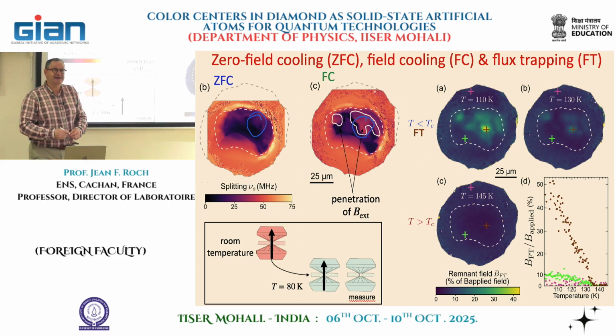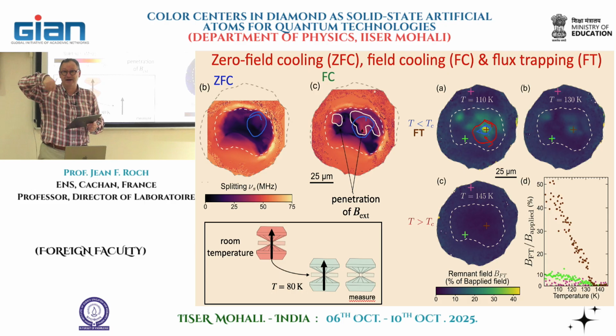And what you see is that the superconducting currents create some areas just above the sample that emit magnetic flux. This is due to currents circulating here that were responsible for the difference between the field cooling and the zero field cooling images, which were due to magnetic flux really trapped inside the sample. So that's another proof of the existence of superconductivity, at least for type 2 superconductors.